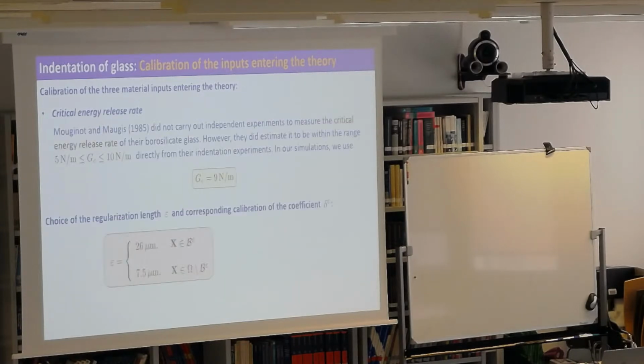Having said that, when we use this theory, the thickness of the phase field crack is not epsilon anymore, right? So we know that essentially it's 2 epsilon or a factor of epsilon. It is affected by delta epsilon. So the actual size of the regularized crack that you see in the solution depends both on epsilon and delta epsilon. In fact, it's smaller than epsilon. And the more you increase delta epsilon, the smaller it is.